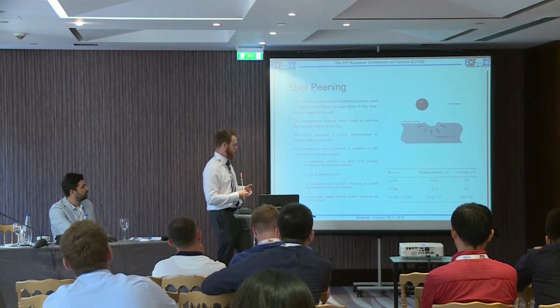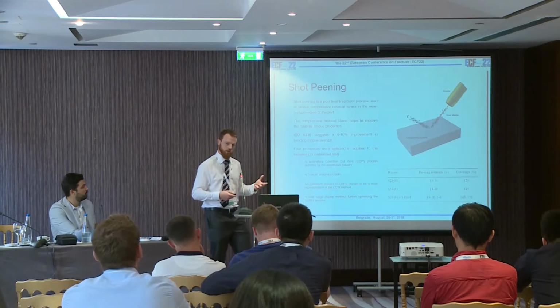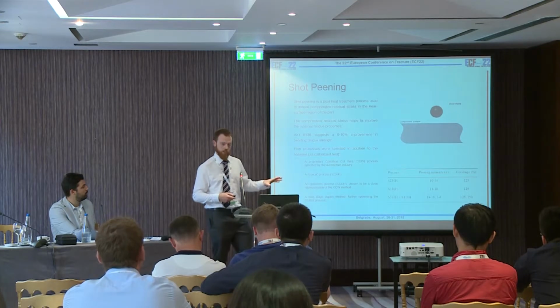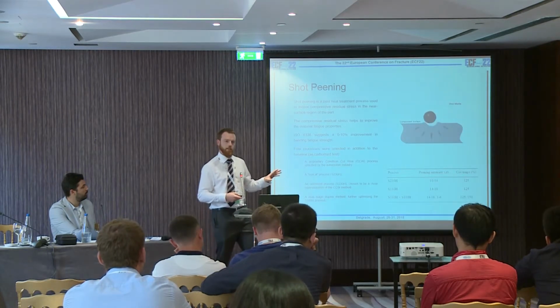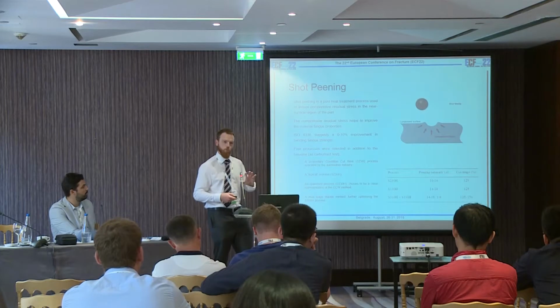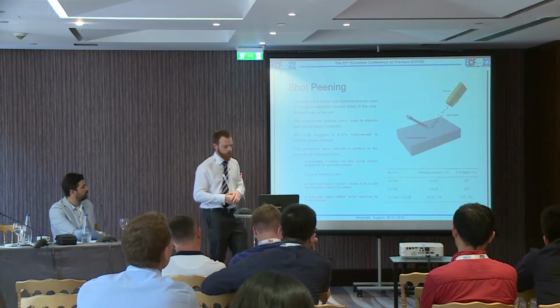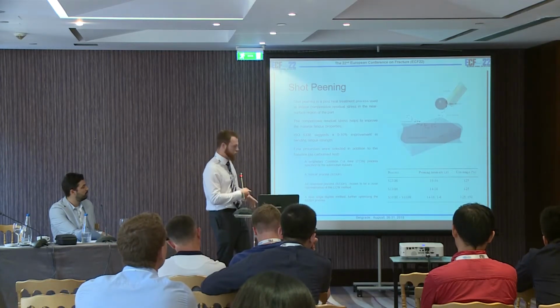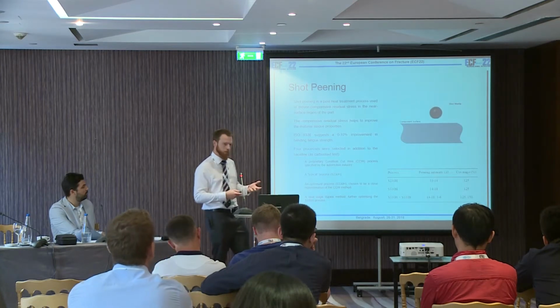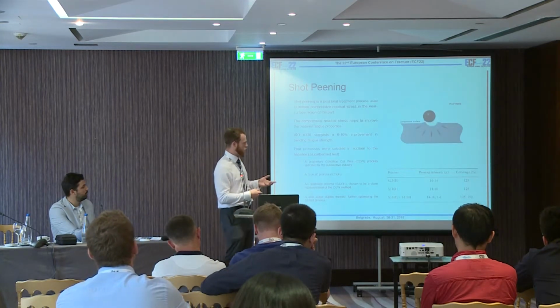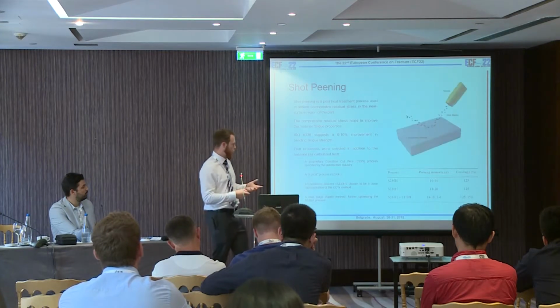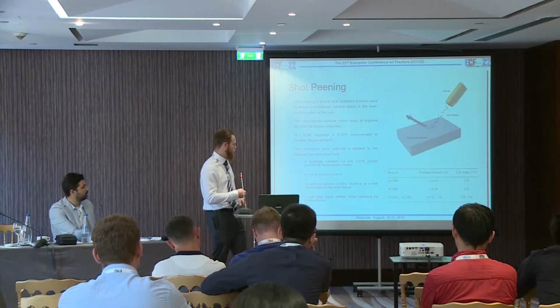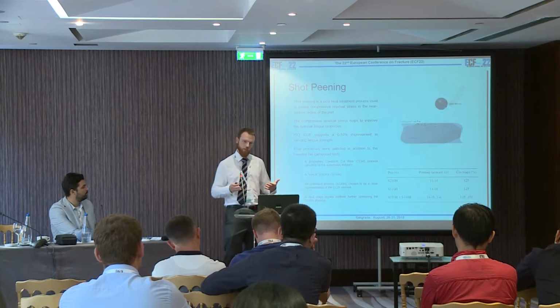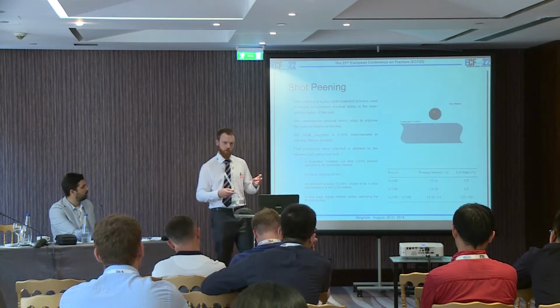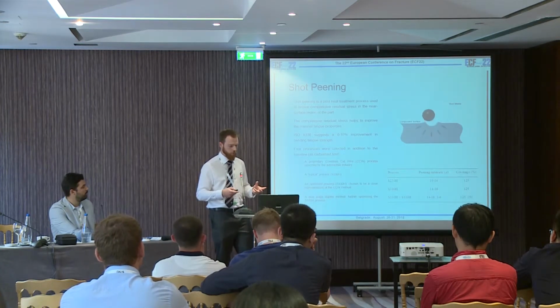ISO 6336, the standard that describes contact fatigue and bending fatigue calculations, tells us that we can see a suggested improvement between 0 and 10% in bending fatigue strength, depending on what quality of steel we're looking at. So of the processes we could choose, there's a number of different media you can look at. The process selected for this particular package of work was a proprietary conditioned cut wire process, so that's taking a section of wire, shearing off sections, and then treating them to create your somewhat spherical media.